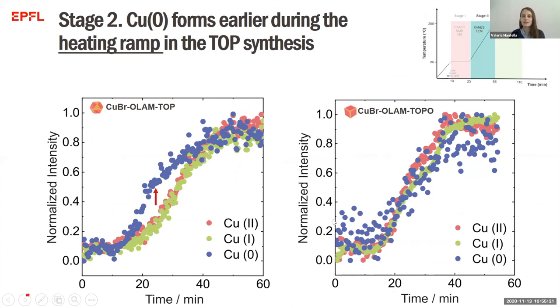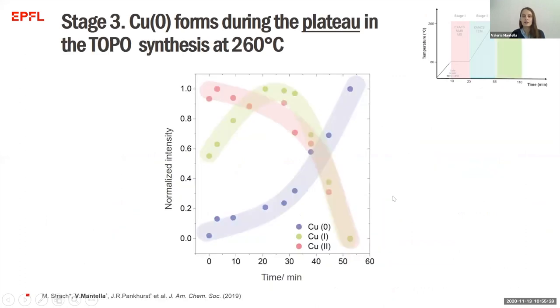Instead, during the synthesis with TOPO, the three chemical species all follow the same kinetics until we reach the plateau at 260 degrees. Now we can see that already during the synthesis with TOPO, already after 10 minutes from when the plateau is reached, we have a rapid increase in the signal of copper zero, while at the same time the signal of copper one and copper two decrease in intensity.